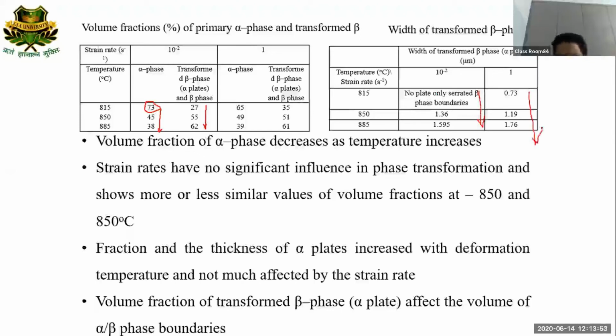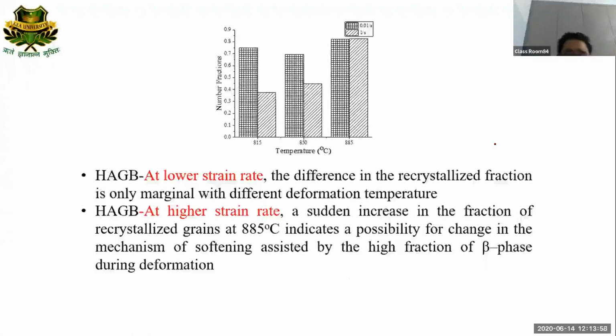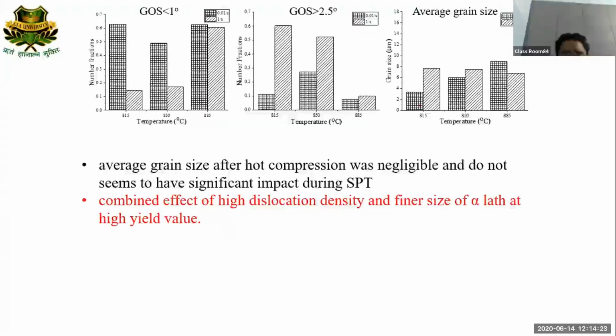Okay. So some rigorous analysis is done on this microstructure, and here you can see the number fraction of high angle grain boundaries. Some EBSD measurement was done on selected samples, and from the EBSD measurement I have plotted the high angle grain boundary fraction for all those samples. Okay, so some information we have calculated from here. Later on, the grain orientation spread we have developed from the EBSD measurement, especially on specific conditions where we have done the SPT samples. The number fraction of GOS less than 1 means the area where recrystallized fraction is there. Okay, GOS greater than 2.5 is a kind of deformation behavior,